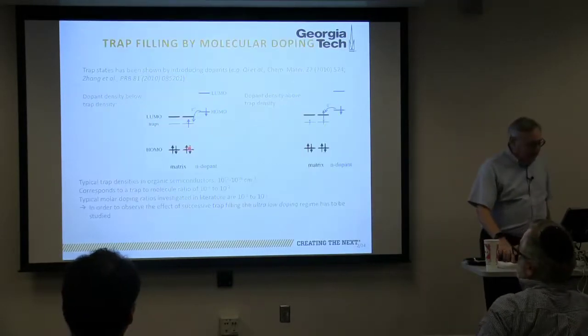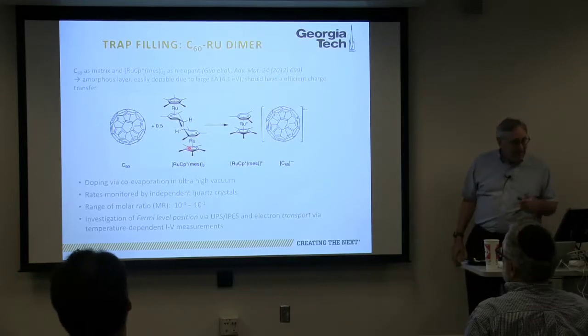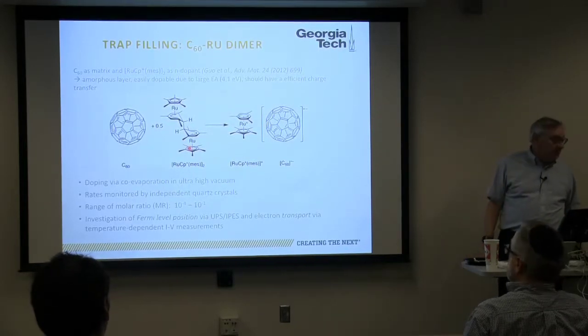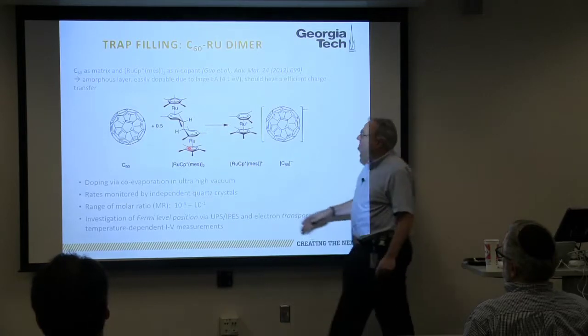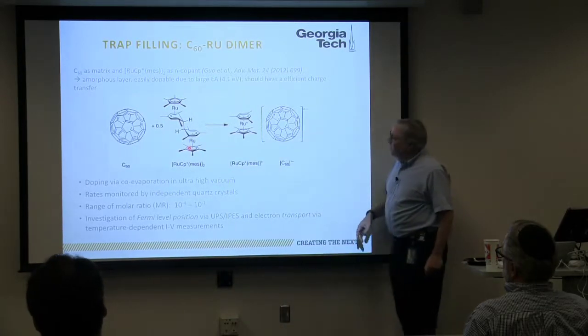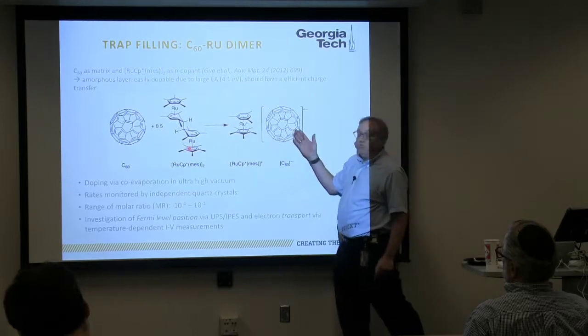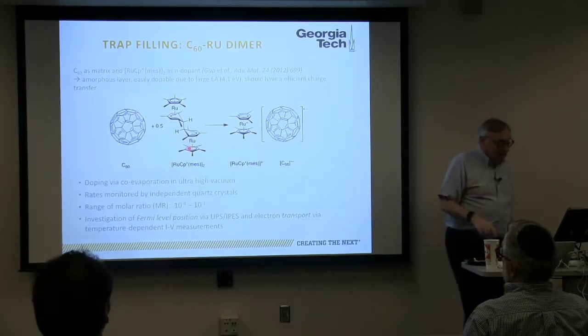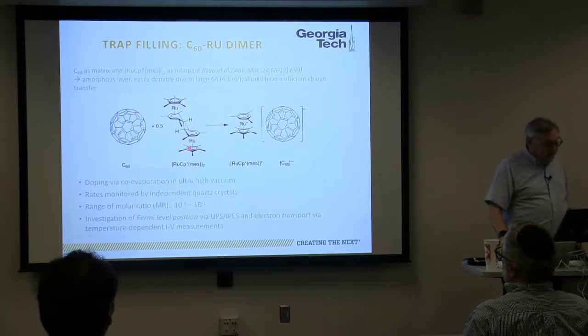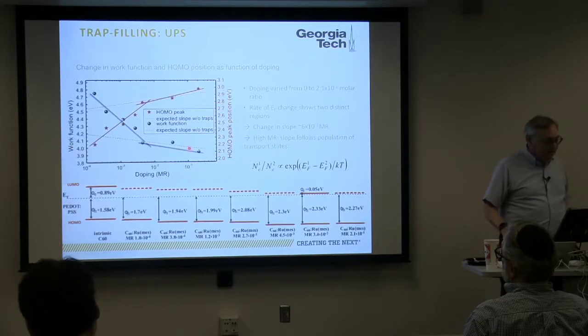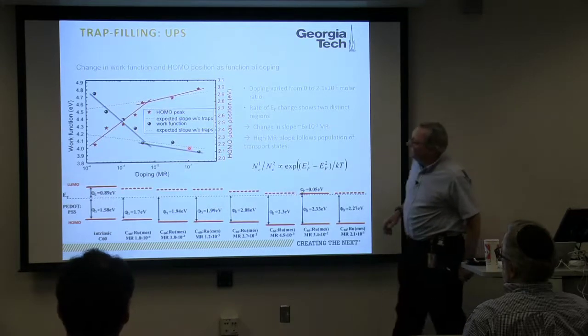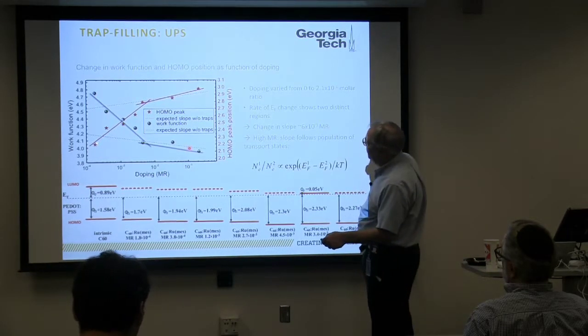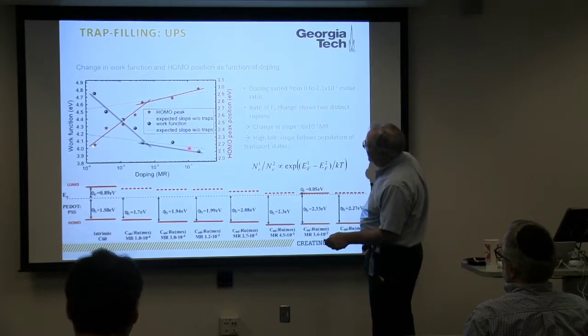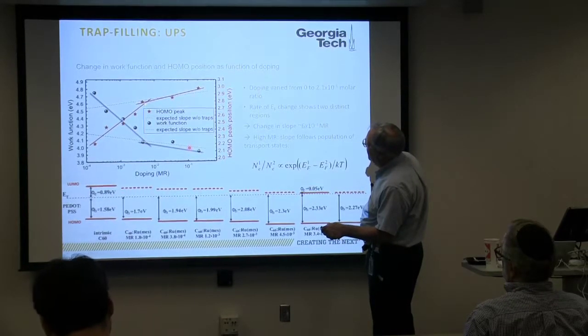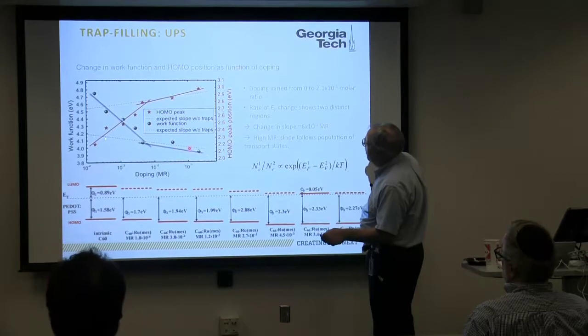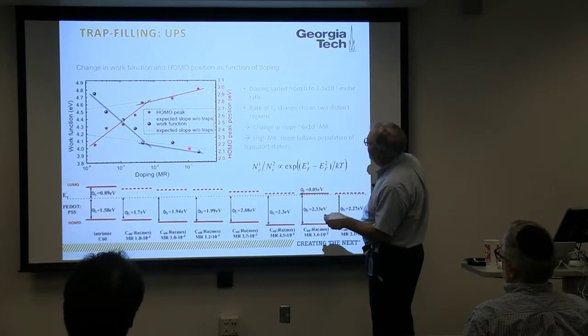Okay? And when you do that, the example that this was done on was C60, and the dimer was one of these dimers based on a ruthenium cation. What you can do is if you heavily dope, you can just reduce and make the ruthenium anion. Okay? But if you very lightly dope, then you'll just fill the trap states. And in fact, what you see is that when you look at the work function of the material and the HOMO position, you'll see that there are two regions for the work function and the HOMO position.